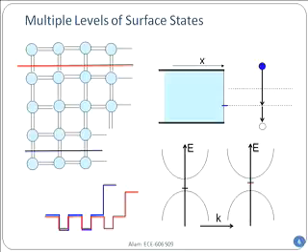Okay. Now as a result, there will be a corresponding electronic state, but see here, the red is at a slightly different position in the conduction band. You see that? And as a result, now again you will have another electron recombination path, but it will be through a different state. So what is happening here is that the surface is sort of non-smooth. Had it been an absolutely smooth surface, there would be only one defect or only one surface state. Because of this surface oscillation, there will be a series of them essentially populating the entire band gap.